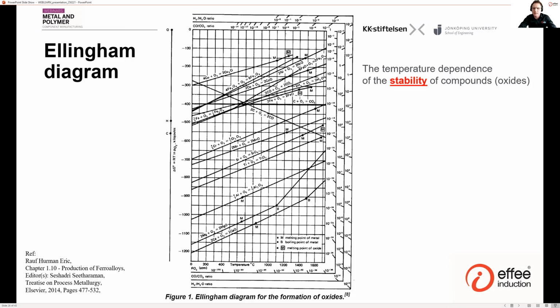In the iron carbon diagram, it's carbon that is in focus, of course, but carbon is also very much influenced by oxygen in the melting process, and the stability and temperature dependence of formation of different oxides can be seen in the Ellingham diagram, where we have on the y-axis the driving force, delta G, of formation of the oxide, for different alloys forming oxides with oxygen.